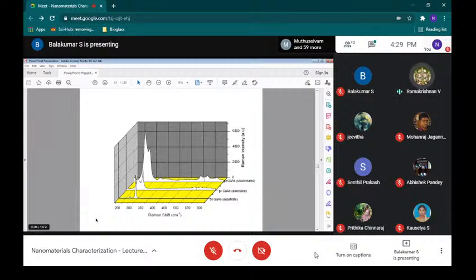So when we go for the P plus, P-rich gallium arsenide, it still shows the forbidden mode more intense than the allowed mode, but when you anneal, the ratio becomes less than 1. So in a P-rich situation, when you anneal, what happens? The forbidden mode is less intense than the allowed. If you take the ratio of the forbidden with respect to the allowed, the intensity ratio is less than 1, whereas in this case the ratio is greater than 1.